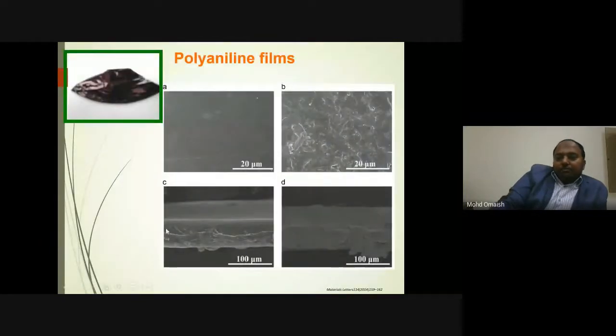And apart from this powder, polyaniline can be easily processed into films, flexible films. For example, you can get emeraldine base, which you can solubilize in NMP, DMSO, DMF. NMP is best. If you want, you can add some nanoparticles like graphene, carbon nanotubes, or some other thing, and you can get a very good flexible film of polyaniline by the solution casting method.